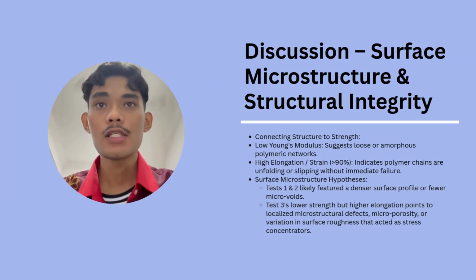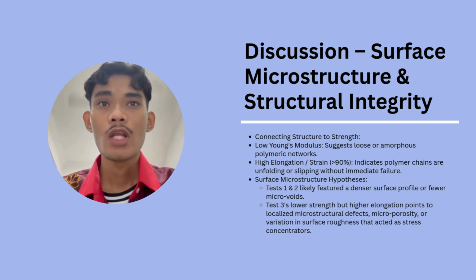Let's connect these mechanical numbers to the material's surface microstructure and structural integrity. Because the material stretches so much, averaging nearly 95% elongation, we can conclude that its internal structure consists of highly flexible rubber-like chains that easily slide and unfold when pulled. But why did Test 3 break at a lower force while stretching further? When we look at structural integrity, the surface of a material is highly critical. Test 3 likely had microscopic imperfections, tiny air pockets, or small surface variations on its skin. These tiny defects act as weak spots. They caused the sample to yield early at just 123 newtons, but because the rest of the material was still healthy, it kept stretching out like a rubber band.